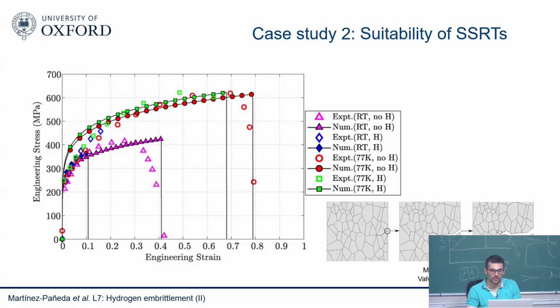And they saw that, so this is a seminal paper in the area, the hydrogen in the grain boundaries was enough to trigger embrittlement. So even at 77 Kelvin, you put hydrogen, you see embrittlement mechanisms. So we saw we could capture that. We reproduced this with this model, and indeed, you can see the agreement is relatively good.